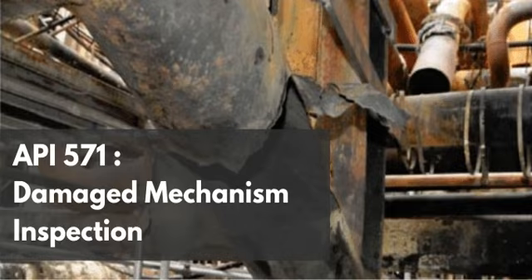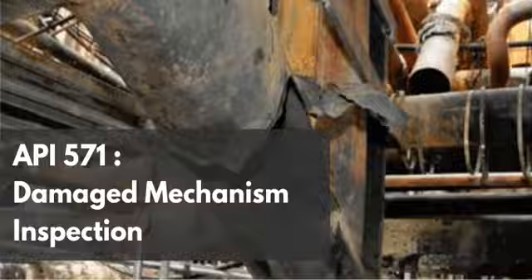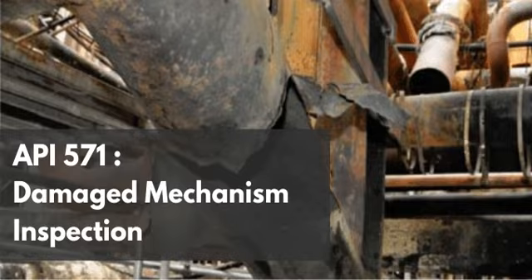Not at all. It is a far more robust, integral process. Alonizing is a proprietary thermochemical diffusion process. So it's baked in. Yes. Instead of waiting for carbon to diffuse into the steel in the refinery, the manufacturers intentionally diffuse pure aluminum into the surface of the steel in a controlled factory environment before the tube is ever installed. They bake the aluminum deep into the outer skin of the metal. So they are essentially preloading the atomic lattice with aluminum.